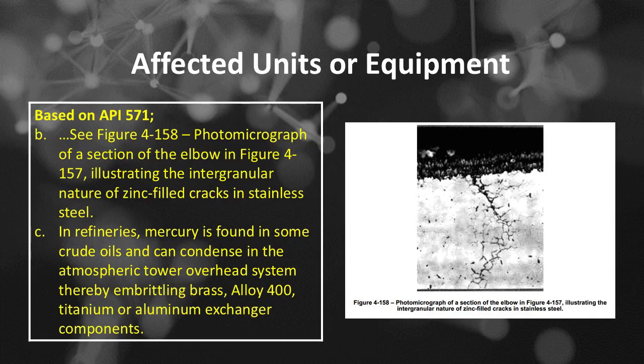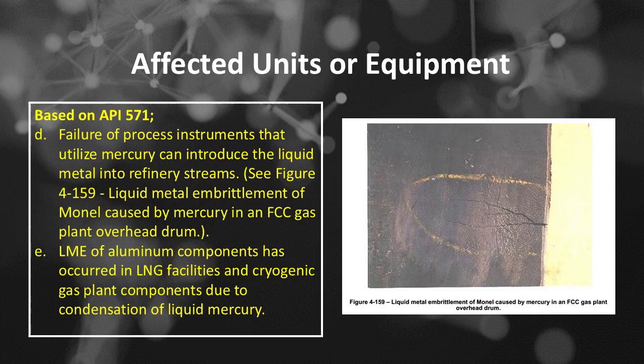Number C. In refineries, mercury is found in some crude oils and can condense in the atmospheric tower overhead system, thereby embrittling brass, alloy 400, titanium or aluminum exchanger components. Number D. Failure of process instruments that utilize mercury can introduce the liquid metal into refinery streams. See Figure 4-159, liquid metal embrittlement of Monel caused by mercury in an FCC gas plant overhead drum.